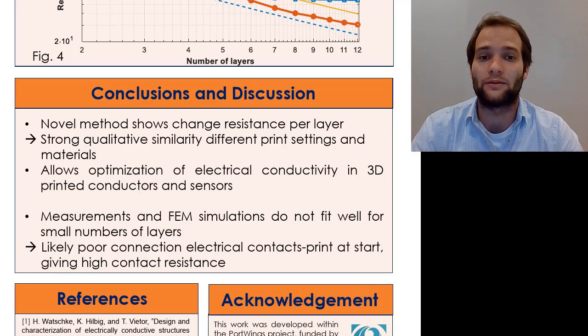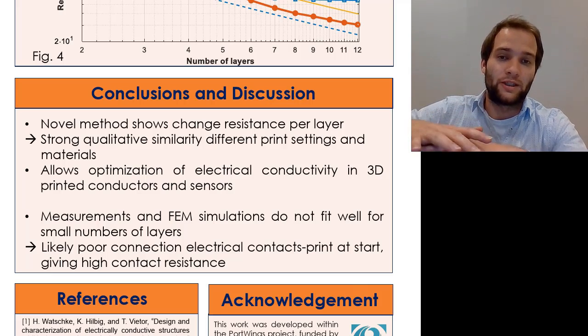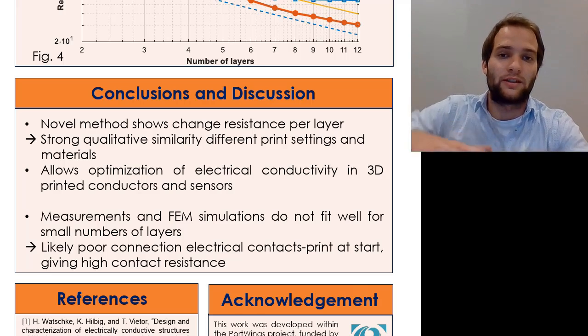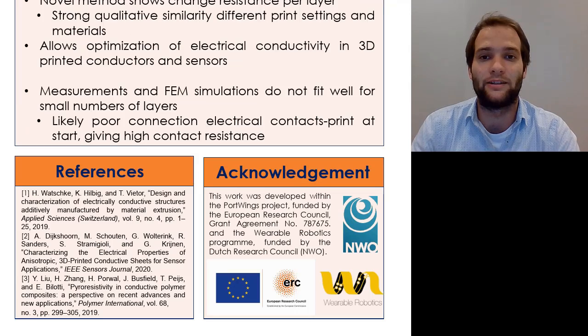The measurements and the finite element method simulations do not fit well for small numbers of layers. This probably can be explained by a poor connection between the electrical contacts in the print at the start, giving a high contact resistance, which is lowered when the printer heats up the material, anneals it, and pushes it together onto the contacts. This was my presentation.